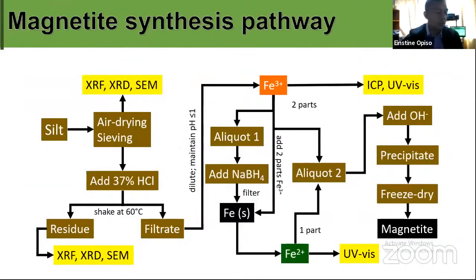So here is our final magnetite synthesis pathway. After several attempts, we were able to come up with this synthesis method using the co-precipitation method known in literature, but with some minor modifications.